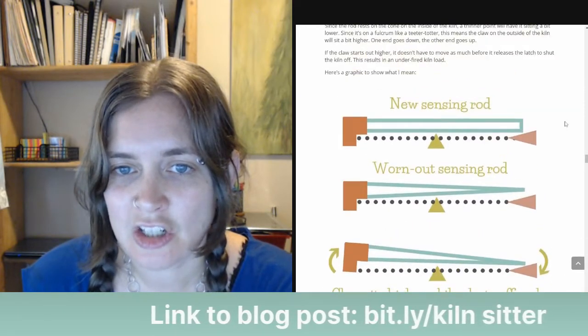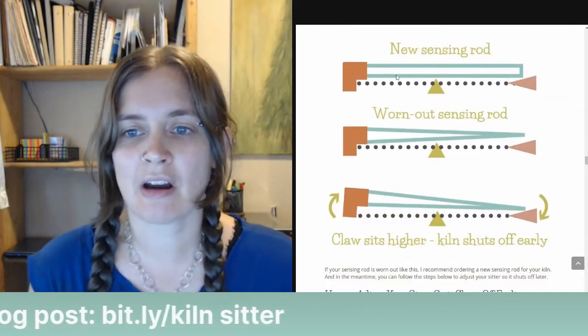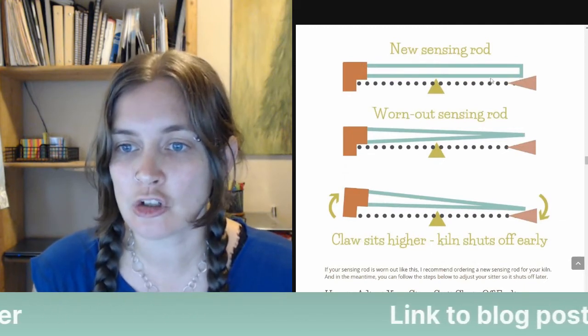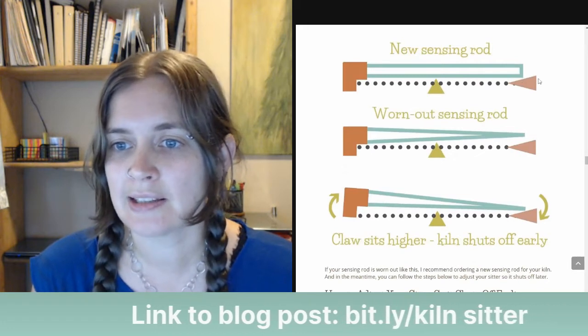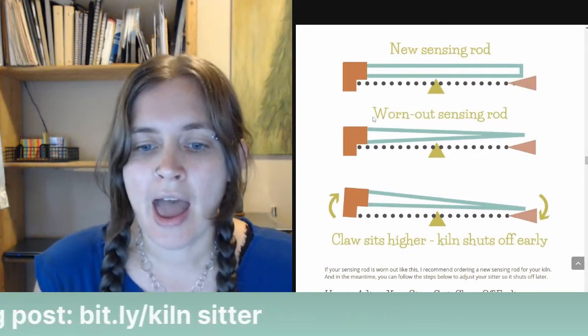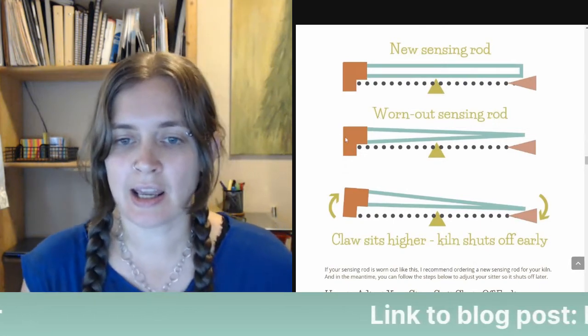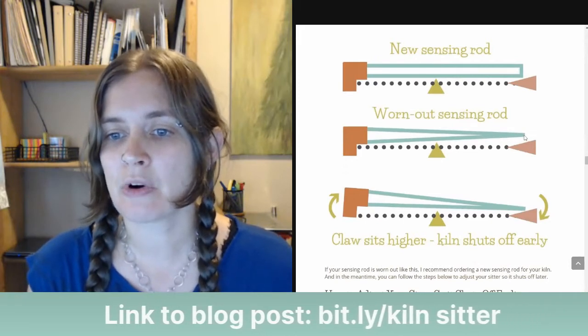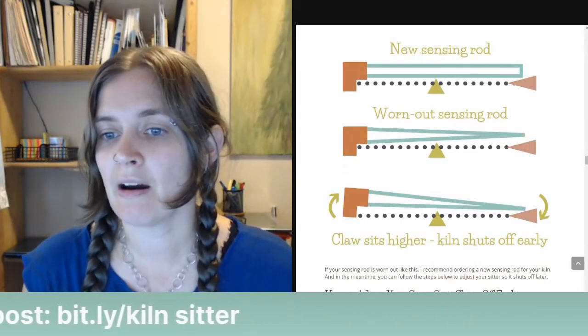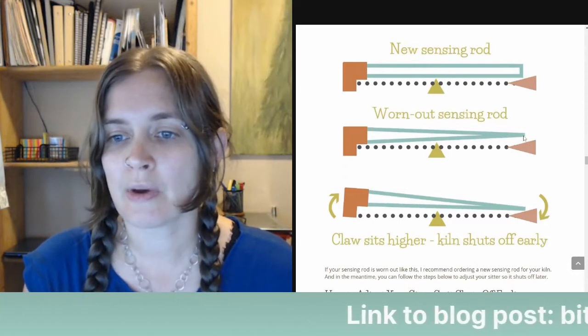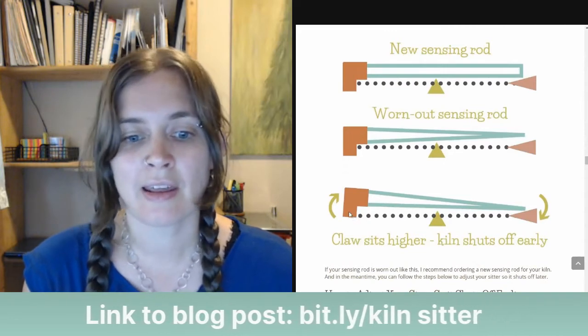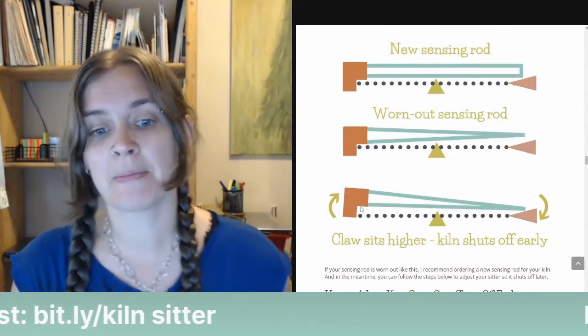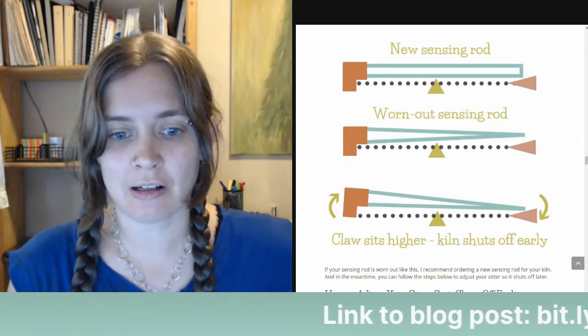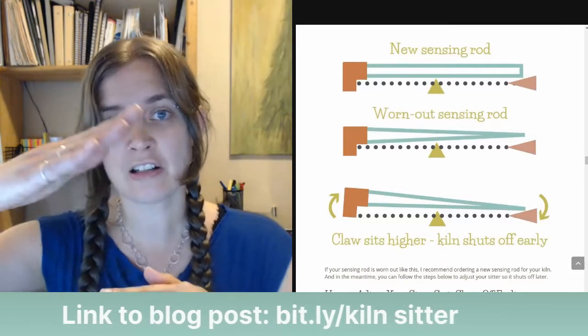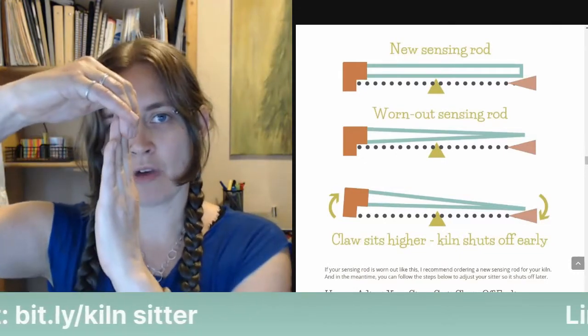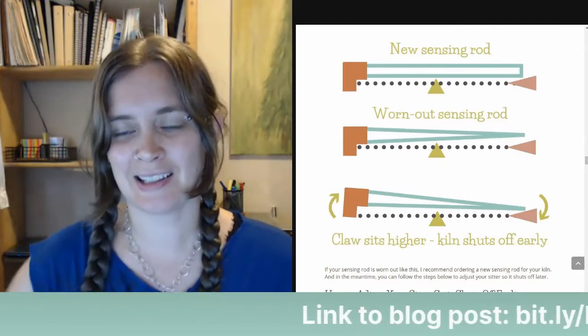So here's a graphic to show what I mean. This is a new sensing rod here, and as you can see, it's cylindrical, nice and uniform. And so it sits touching the cone. Now if you have a worn out sensing rod, if it's sitting at the same angle, because it's worn down to a point, the point is going to sit a little bit higher compared to the cone. And so when this goes down to touch the cone, the claw on the outside of the kiln moves up, which means your kiln is going to shut off a little bit earlier because it just doesn't have as far to travel before it releases the trigger plate and lets the kiln shut off.